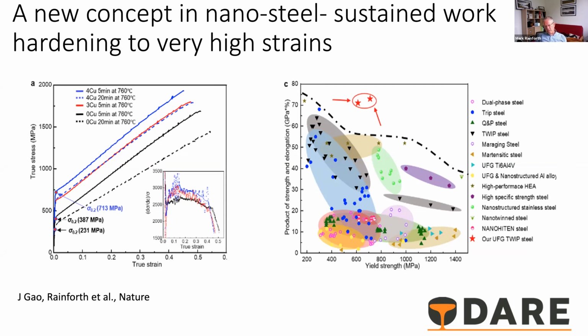And so what we believe is that the copper precipitates are not actually giving you strengthening per se. You just get shearing of dislocations. They seem to be able to go through the precipitates really uninhibited. But what the copper is doing is stabilizing that very fine grain size of 1 micron or thereabouts. And then the deformation mechanism is in fact through a twinning mechanism, which is quite different.